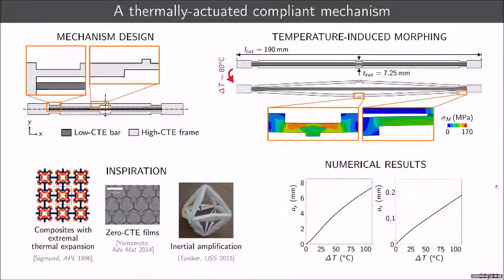What you can see is that the horizontal displacement is very small. It corresponds to really very small strains, microstrains, while the strains along the vertical direction are actually macroscopic. In fact, you can see that at 100 degrees Celsius, you have a displacement of more or less 7 millimeters, which is comparable to the size of the specimen. So we actually almost double the height of one of these cells in response to temperature.